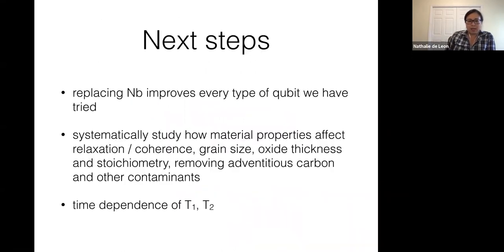So basically, we have found that replacing niobium with tantalum improves every type of qubit we've tried, regardless of surface participation ratio and geometry. And now we're working to systematically study how various material properties affect T1 and T2, like the grain size of the tantalum, the oxide thickness, and stoichiometry. And we're also working to remove this last layer of adventitious carbon and other contaminants at the surface.